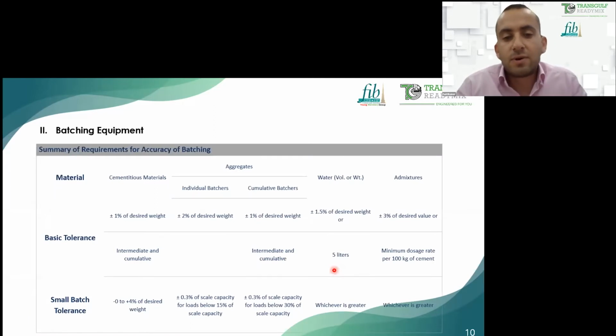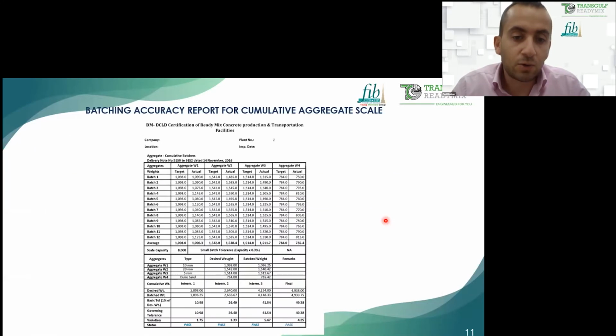Then, including the batching equipment, we verify the batching accuracy. As an example, for the cementitious material we have a limit of plus or minus 1% of the desired weight, and for the admixture it's plus or minus 3% of the desired weight. This is verified through collecting data from the operating system of the batching plant.